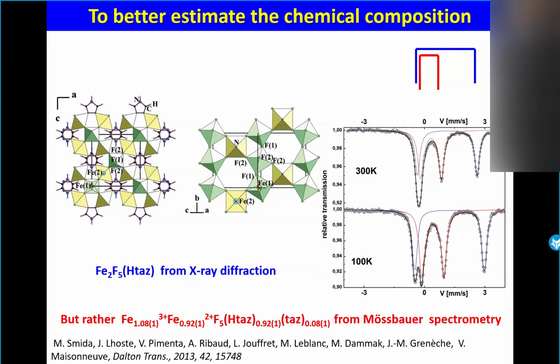So what we did was to go to lower temperature. At 77 K, the system is magnetically ordered, so we limit ourselves to 100 K, just above the magnetic ordering temperature. And of course, this solution was the best one. So now the problem is 53-47. Oh, it's not possible. I'm sorry, but usually Mössbauer is right.